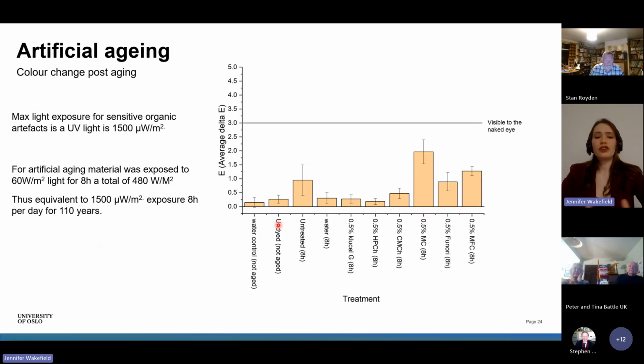In terms of artificial aging, we tried to replicate the light exposure for the sensitive organic artifacts. So that would be 1,500 microwatts per meter squared. And we wanted to see, for about 8 hours exposure a day for 100 years, 110 years, whether or not we would see a color change. So we used a very strong light for 8 hours to sort of replicate that.